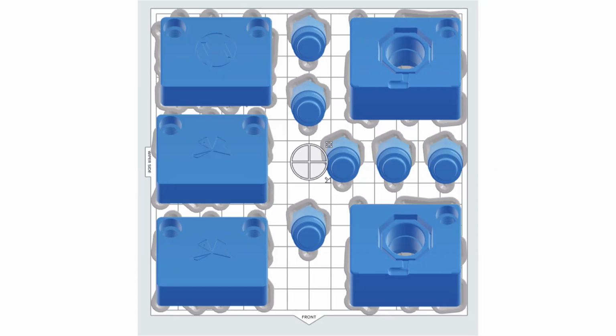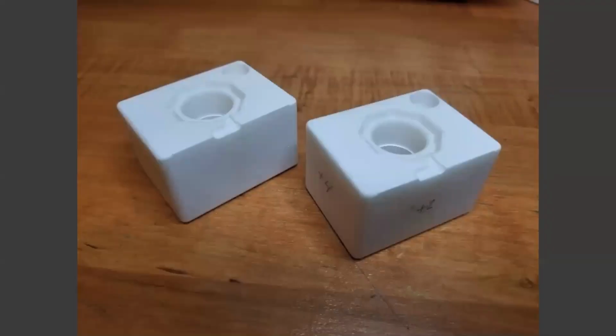Specifically so that when we start to finish the block, we've done it via sanding, a simple milling machine operation, things like that. But you need to have a couple square sides that you know you're working off a good reference edge. Otherwise, your blocks can be out of parallel, out of size. So we closely watch orientation, then we trim and clean, we do a full cure, and then we do some minimal grooming. Emphasis would be we did not touch the molding surface at all. So all of the molding sizes, the logos, everything was done.